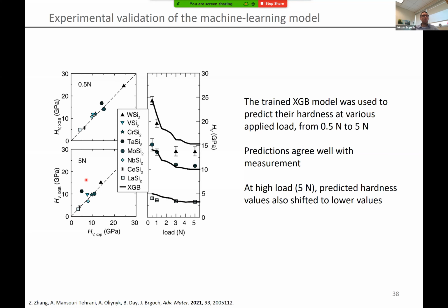Where we were really excited is that if we plot the load response curve—apply higher load, hardness drops—we're able to capture this almost perfectly with the XGB model for all of these different compounds. I'm showing 3 here, but all 8 show reasonable reliability. It's worth pointing out, though, that these are only up to a hardness of about 26 gigapascals, and we're interested in super hard materials.